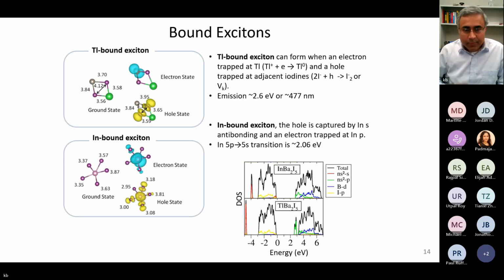Is that going to happen? We did some more work on these Ns2 compounds, and we found that indeed they might be. This was just our prediction at that time, that you may not need an activator. You do not need an external activator to dope these Ns2 compounds. They might just luminesce by themselves, meaning they might be self-activated. How so? We found for the thallium compound, for example, thallium barium iodide, that they can create a thallium bound exciton. What do I mean by that? For an exciton, you need an electron-hole localized pair, right? That's an exciton, generally speaking.